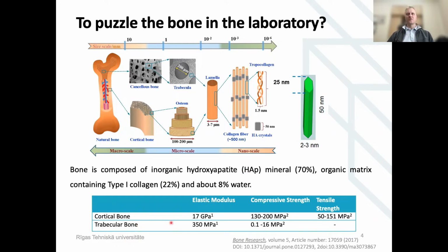properties. So the easiest for us to understand is the compressive strength, 130 to 200 megapascals for cortical bone. And that means about 2,000 kilos per square centimeter. So if you imagine one car, a normal car, put on a 1 centimeter by 1 centimeter area, or let's say on the tip of your finger, that's the pressure the bone can withstand. And this comes from this unique combination of the mineral phase that gives the mechanical properties, and also the collagen, the organic phase, that gives the rigidity.